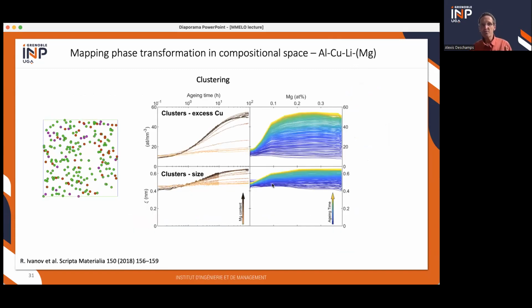Then you can do experiments where you scan continuously this composition gradient during time. And we did that first at room temperature, very simple. It's easy, you don't need a furnace. And to study the effect of magnesium on clustering of copper.